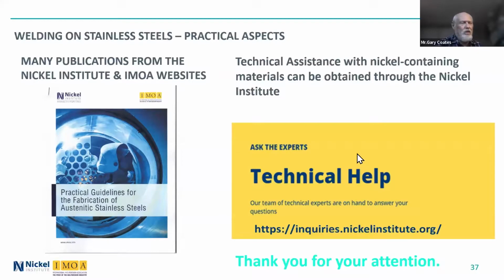And should it be a mandatory check? Well, if it's important, it should be. Generally, you should try to avoid high ferrite welding electrodes that end up with more than 10% ferrite. Even if they do weld nicely, generally more nicely than the lower ferrite ones, you should avoid them. But it should really only be a mandatory check when it is actually significant, and hopefully the engineering company that writes the spec will know when it is significant.